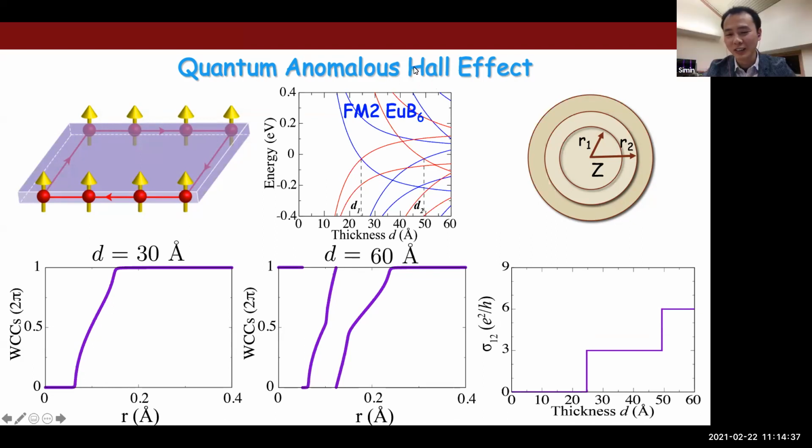Yeah. So this is on the bottom right-hand panel. So my question is what is the origin of having such large Chern numbers in the quantum well structure of this Europium hexaboride? First, the Chern number, because the subsequent jump of the Chern number is 3 in this material. So which means you can realize a Chern number of 3 times n, where n is the number of jumps. So yes, of course, you can reach as large as you want by increasing the thickness of the thin film.